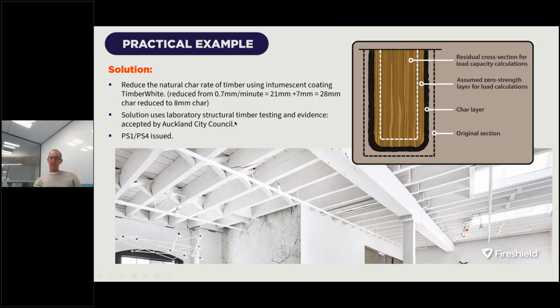Here's the solution for this example. That's what they wanted it to look like. Loft style, exposed ceiling, exposed floor, underside floor joists and supports. So we were able to reduce the natural char rate of the timber using our timber white coating. We reduced it, as I said, from 0.7 mm a minute or 28 mm, and we reduced it to 8 mm. So 8 mm of char off all those members was enough to, after a 30-minute fire event, the remaining timber member was able to give the structural stability required to support that floor still, which is what they needed to achieve.